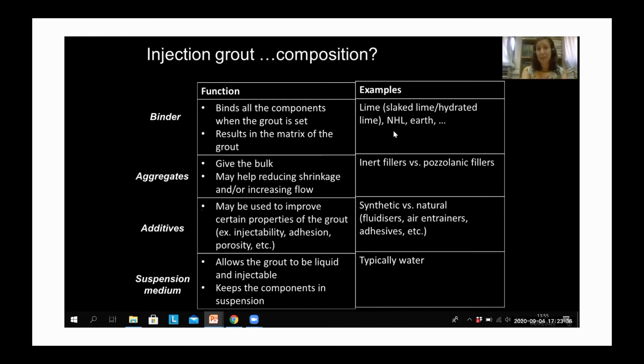So some examples: for the binder, we can have lime, which can be slaked lime, hydrated lime, we can have hydraulic lime, we can have earth, we can have gypsum. So different kinds of binders according to the original materials. We can have, in terms of aggregates, inert fillers or pozzolanic fillers. They will give the suspension and then the dried grout different properties, and also will lead to different chemical reactions. And we can have additives which are synthetic or natural. And as I mentioned before, we can have various types of fluidizers, air entrainers, and so on. The suspension medium is typically water. And of course, as wall paintings very often face problems of soluble salts, typically deionized water is used.